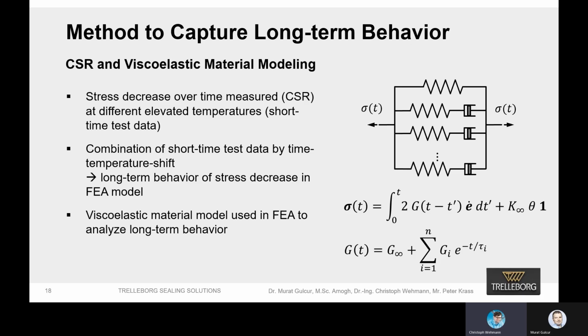At the bottom, you see how the shear modulus decreases over time. We have an infinity shear modulus, which is connected to the spring at the top, the equilibrium spring. Then we have G_i, which means the shear modulus of each network, and we have theta_i, which is the relaxation time of each network. With such a model, we are able to feed in CSR data, compressive stress relaxation, and then do FEA simulations to predict the lifetime long term.